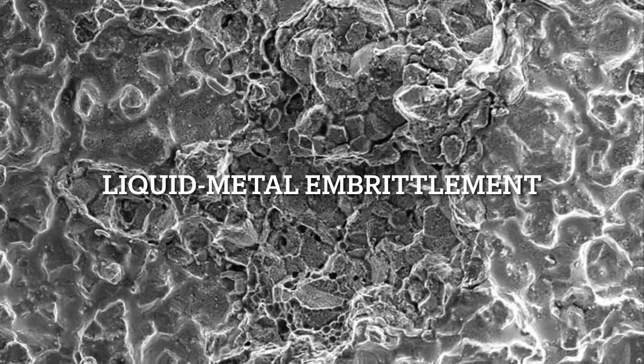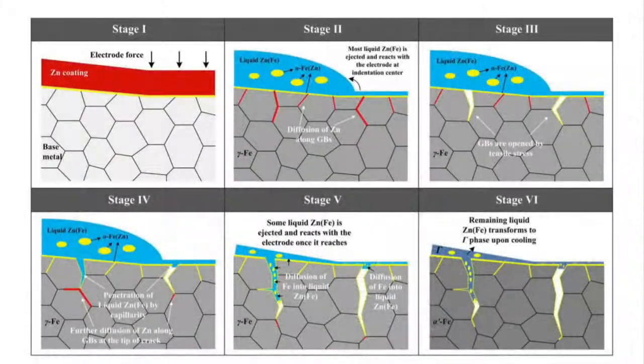Then we move on to the third mechanism, which is liquid metal embrittlement. Liquid metal embrittlement is when a normally ductile metal becomes brittle when stressed in contact with molten metal. I will use this example to explain the details of it. Okay, so we straight jump into stage 2, when the liquid metal, which is liquid zinc, is in contact with the susceptible metal, which in this case is iron. Under the stress, it will diffuse along the grain boundaries of the iron.